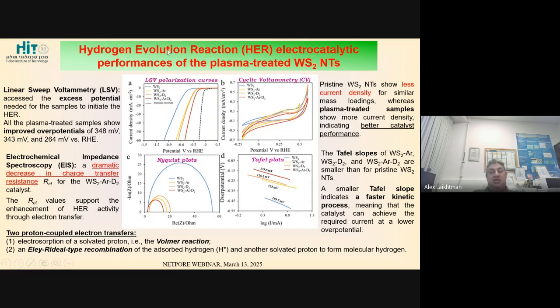But now concentrating on these WS2 nanotubes treated by plasma, we also performed some other measurements. For example, CV, cyclic voltammetry, which shows that for similar mass loadings, the plasma treated samples show more current density, so they have better catalyst performance. The electrochemical impedance spectrometry also confirmed that there is a dramatic decrease in charge transfer resistance for double plasma treated samples. And also the Tafel plots: a smaller slope, as in the case of plasma treated samples, indicates a faster kinetic process, which means that the catalyst can achieve the required current at a lower potential, which is always beneficial.